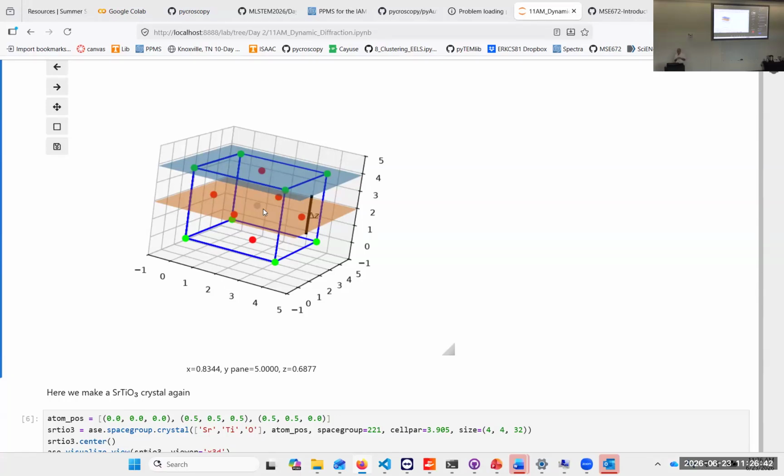So we get our Bragg reflections. What we do next is we calculate the different path lengths, because they all come with different angles, right? For the electrons that hit the second layer, we first have to scatter, and then we have to translate them. That is where the problem comes in. Diffraction we did in reciprocal space, but the path length is in real space.